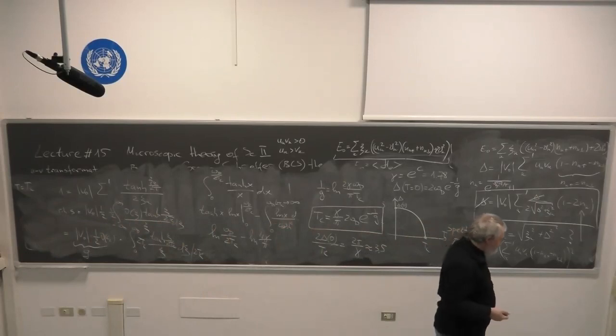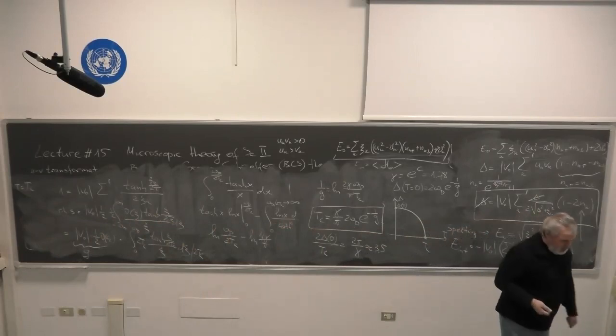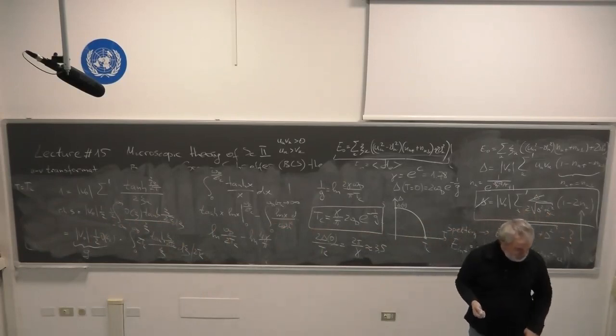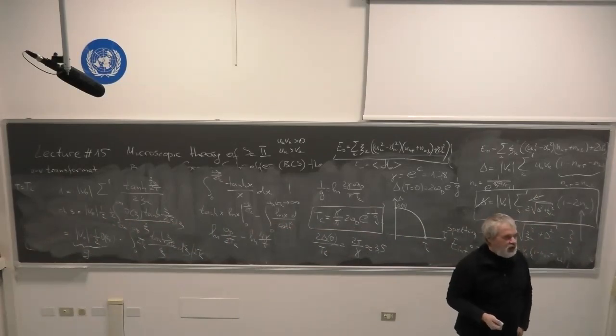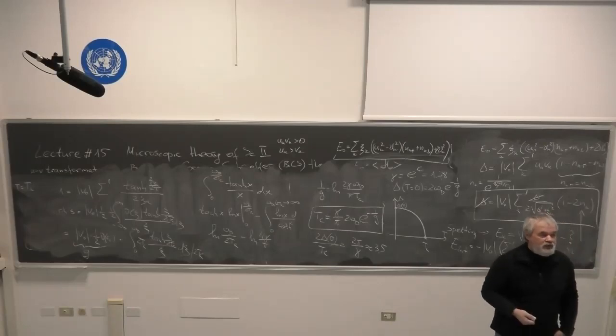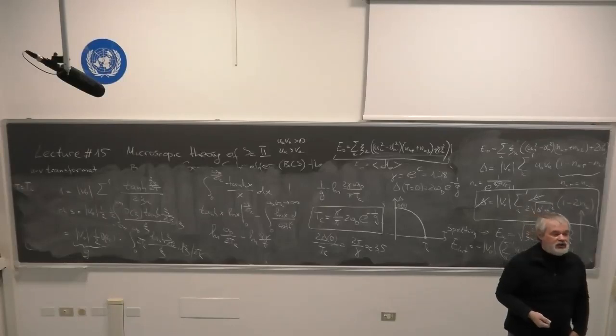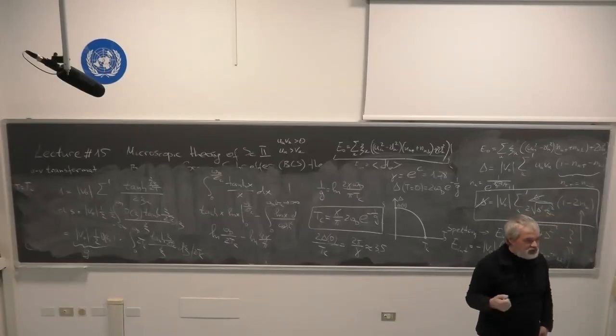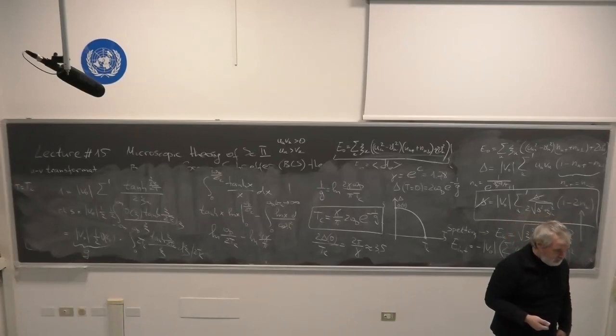When high temperature superconductivity was discovered in 1985, people measured the gap. It can be measured by experiments, in particular the tunnel experiment, for measuring tunnel current gives you directly the value of delta. You can take delta from thermodynamic measurements. You can measure delta through the Josephson effect.